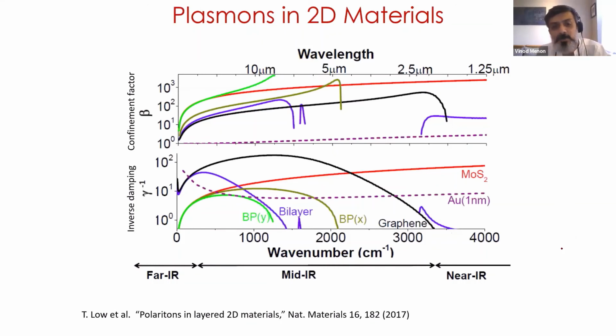So this is just a quick overview from an article by Tony Low and co-workers where they showed that in these systems you can get plasmons in different materials, or plasmons with different properties, but most importantly the damping is very different for different materials, and in fact in some cases you can even get damping rates that are lower than typical gold films and so on at some wavelength range.